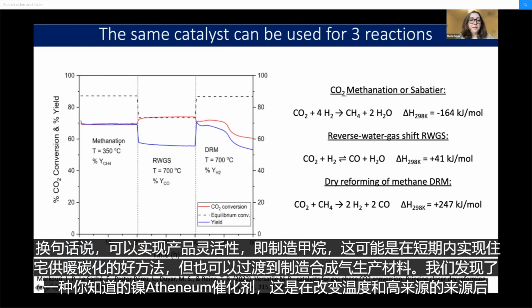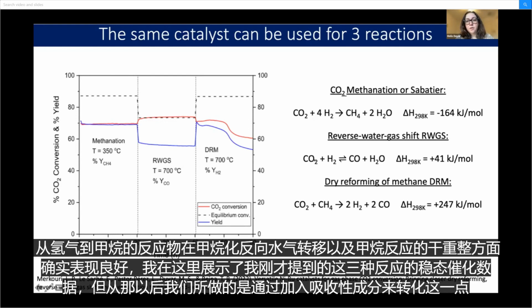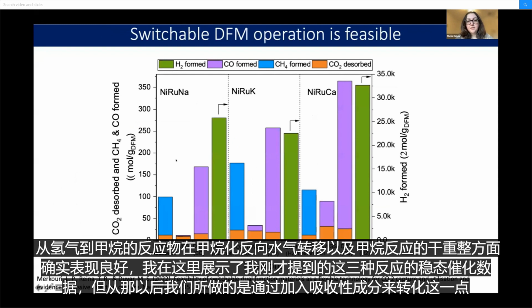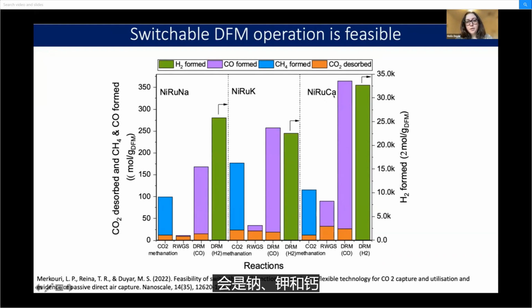We found a nickel ruthenium catalyst that, upon changing the temperature and the source of reactant from hydrogen to methane, does perform quite favorably for methanation, reverse water gas shift, as well as the dry reforming of methane reactions. Here I'm showing steady state catalysis data for these three reactions that I just mentioned. But what we've done since then is to translate this by incorporating an adsorbent component, which would be sodium, potassium, and calcium, to develop dual function materials that can be used for all three of these reactions using just dilute sources of CO2.